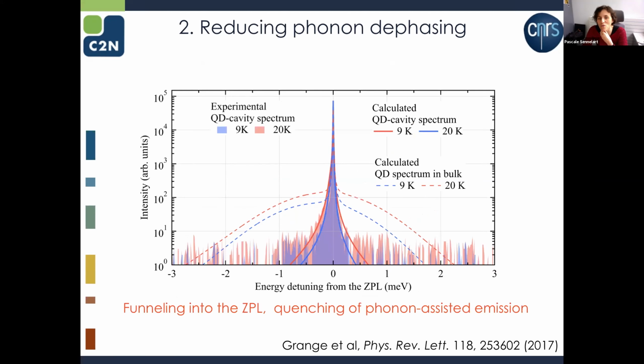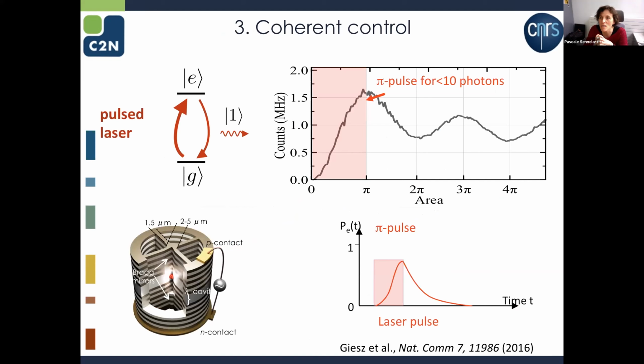And this is what we showed also experimentally. What I was showing before was calculation, and this is experiment where we play with temperature. We warm the sample on purpose to show that we don't gain too much phonon-assisted emission. So we can get rid of phonons quite efficiently like that. And the last scheme to get indistinguishable photons was for us to implement coherent control measurements. The idea is just that we want to bring the system into its excited state in a fully controlled way. And these are techniques that are well known in the atomic community.